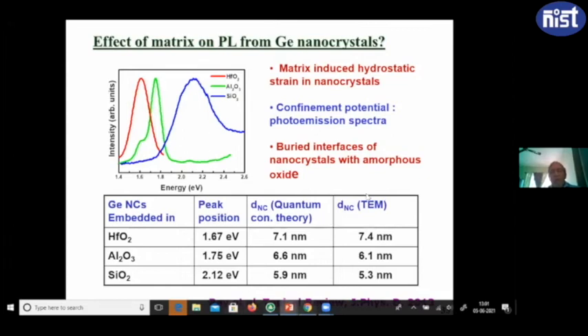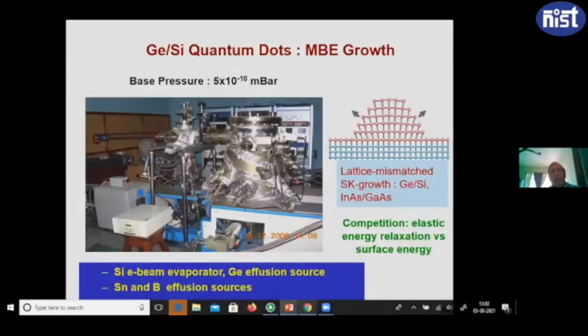And you see that the nanocrystal size measured from the TEM is about 5 to 7 nanometers. This also almost matches with the quantum confinement theory, from which you calculated the nanocrystal size from the emission wavelength. So this actually matches with the theory. This is one technology which can come up for silicon photonics in the future.